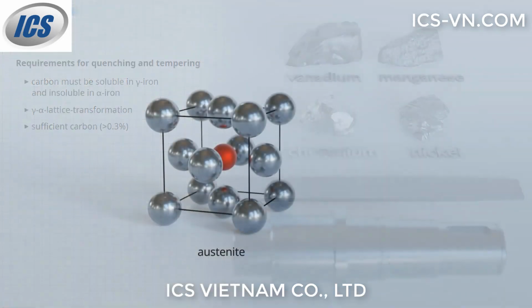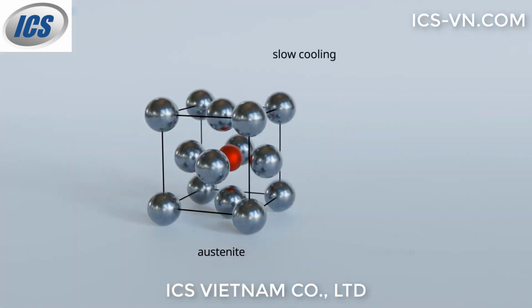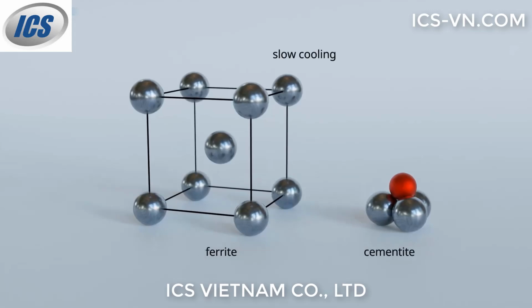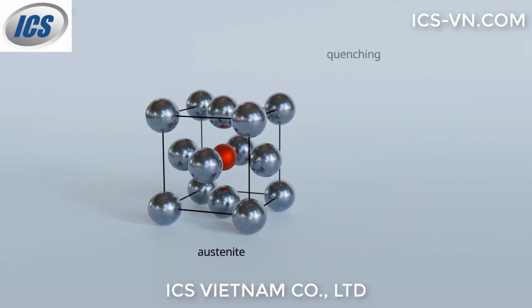The key to martensite formation is to prevent carbon diffusion during the gamma-alpha lattice transformation. This is achieved by a sufficiently high cooling rate.